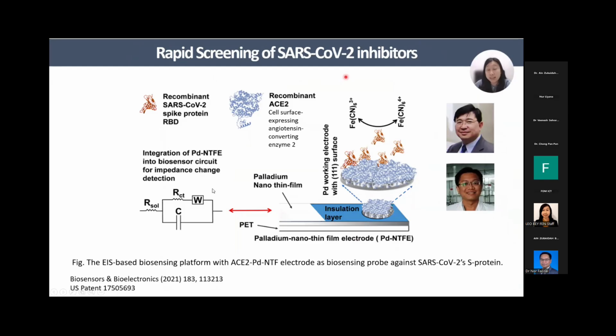As we know, SARS-CoV-2 enters the cell through the binding of its spike protein, the S protein, to the cell surface expressing angiotensin converting enzyme 2, ACE2. So the inhibition of the S protein to ACE2 binding may slow down SARS-CoV-2 cell entry and reduce the progression of COVID-19. In this study, we use an electrochemical impedance spectroscopy, EIS, based biosensing platform consisting of a recombinant ACE2 coated palladium nano thin film as a core sensing element. This was fabricated to screen potential inhibitors against S protein ACE2 binding.